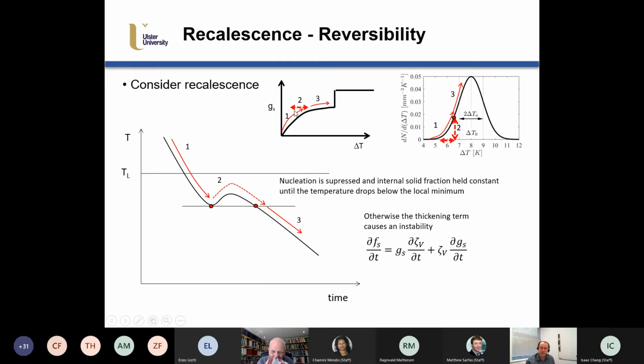So we assumed no remelting or no thinning inside the envelopes. Now, the solidification does proceed. If we look at the breakdown here of the solid fraction, one of these is a thickening term and one is a growth term. The growth term continues regardless of whether there's recalescence or not. It just goes at different rates depending on the undercooling. But the thickening term, we had to prevent from becoming a thinning term.